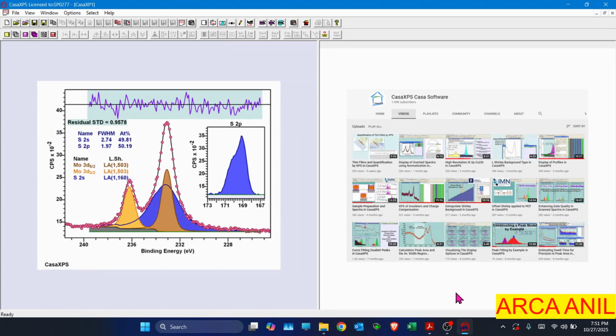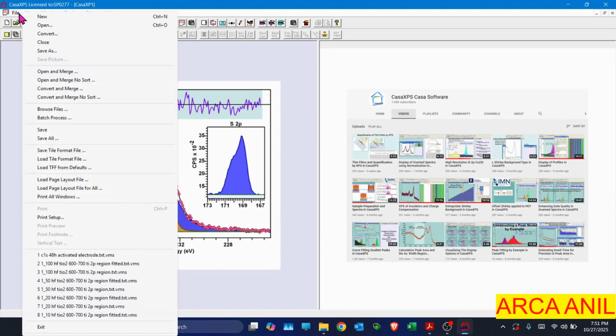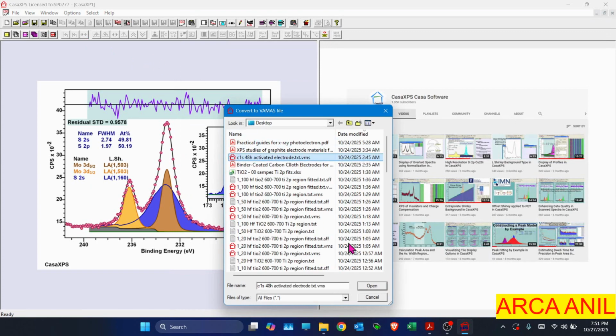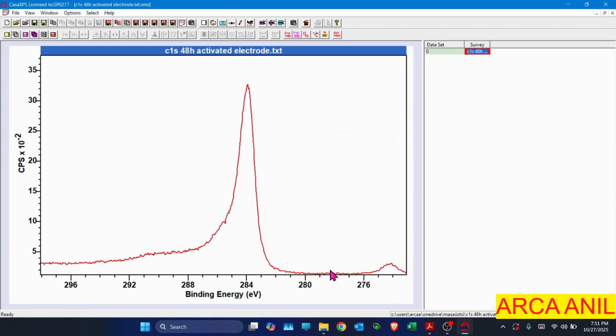So I will open the data file, convert, and activated sample 48 hours. So this is our sample. As you see, in the carbon 1s spectrum, there is a clear pi to pi star transition about here, which indicates the presence of graphitic or graphene-like carbon structures.